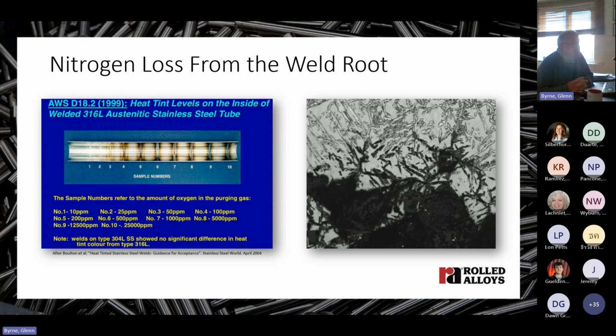Now we can lose up to 20% nitrogen from the root run if we weld with argon shielding gases and argon backing gases in combination. The problem is resolved by not over-purging. Typically, fabricators are asked to purge to an oxygen content that's below 100 ppm, but some fabricators go very low, maybe down to 10 ppm to avoid heat tint. Now for super duplex, it's better to purge in the range 200 to 500 ppm oxygen. Heat tint in these grades isn't as troublesome as in 304 and 316 grade, and a straw-coloured weld's quite acceptable. You can also use argon nitrogen purge gases and argon nitrogen backing gas combinations to avoid nitrogen loss from the root run.